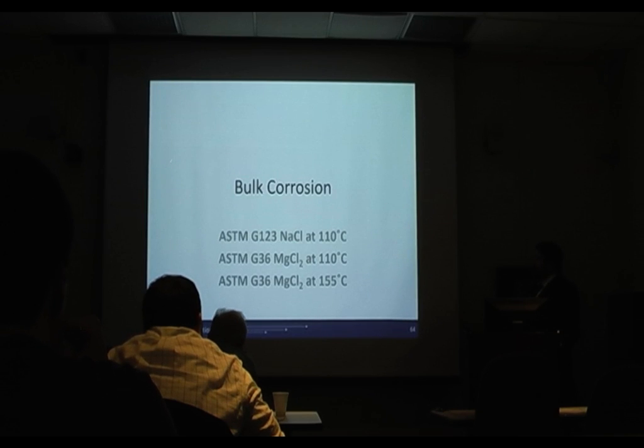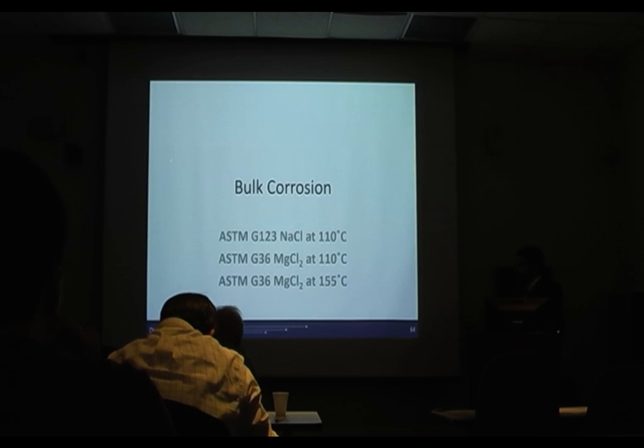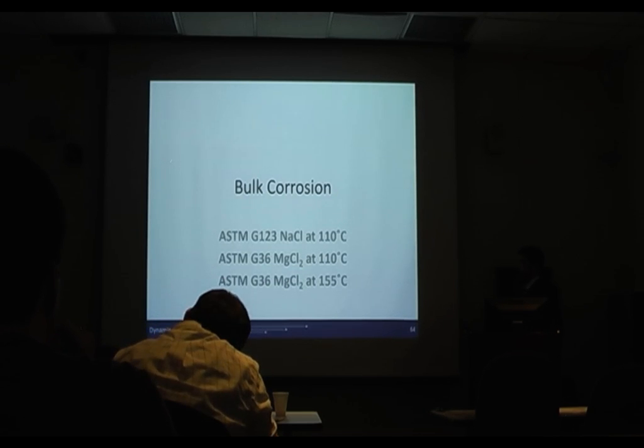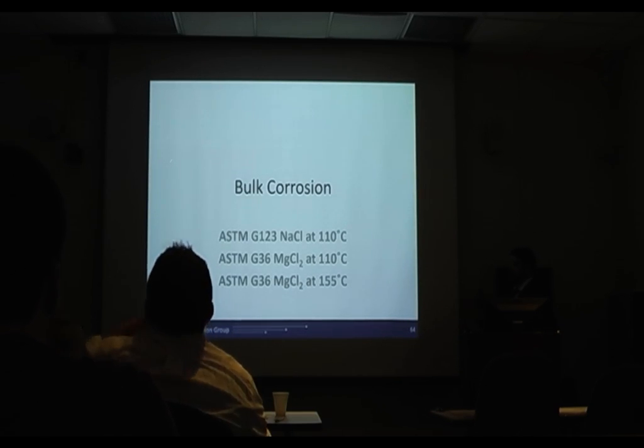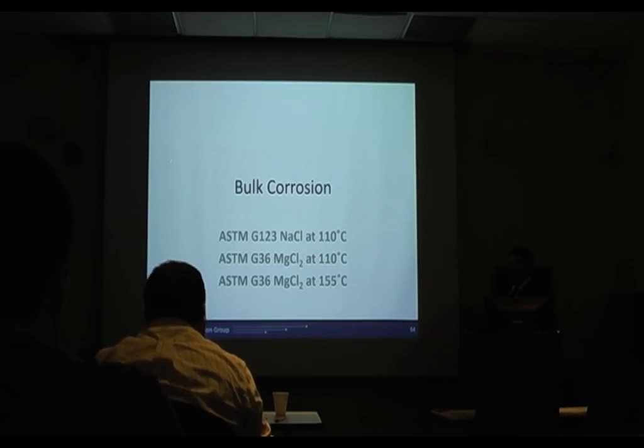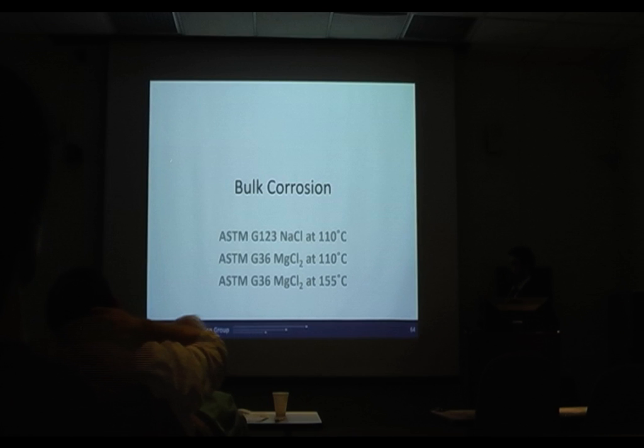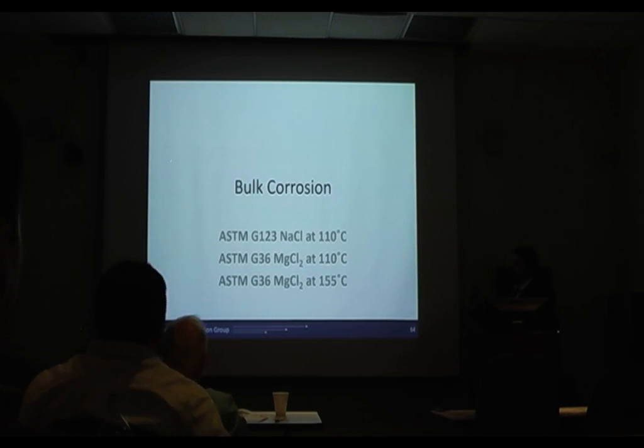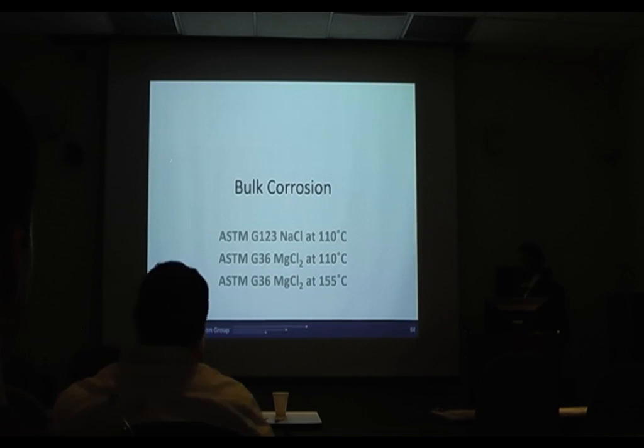So finally, we have our bulk corrosion with the U-bend specimens. This is for testing intergranular stress corrosion cracking. We actually ended up using three different procedures on the same set of specimens. First is the ASTM G123, which is a standard solution of sodium chloride spiked with phosphoric acid that boils at about 110 Celsius. The test is specified to go up to 1,000 hours, and in their interlaboratory testing, every single specimen of 304 and 316 that they tested failed, mostly within 48 hours and all within 2 weeks. And 1,000 hours is right around 4 weeks.